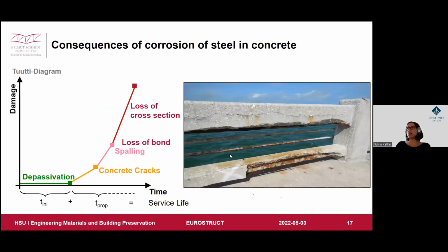Here on the right-hand side, we see now a picture, which I also like to show normally in my lectures, because here you see all the different steps for all the different damages of corrosion-induced damage. Here you see the concrete, the corrosion cracking. So you see the very clear crack, you see the brownish color coming out of the crack, which gives us a hint that here's iron oxide, so corrosion is going on. You see here's a spalling, you see the loss of cross-section, and following here's a shadow, then you can see that here's a reinforcement, it's totally missing. It has been gone due to corrosion. This picture is from a very, very old concrete bridge from the 50s. And you see very nicely how all these different damage situations look like.